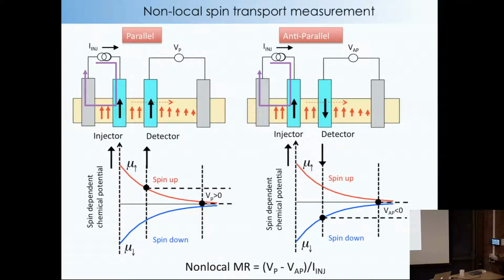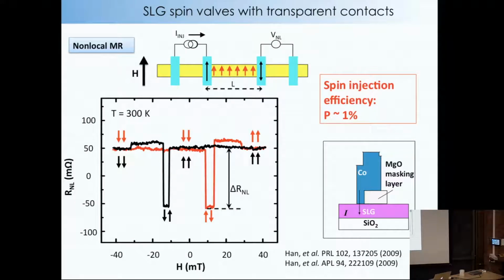So what you typically do is compare the parallel configuration with the anti-parallel configuration. And typically you normalize by the injection current. I mean, if you pump more current in, you'll get more spin density and your signal will be bigger. Okay, so typically you'll normalize this, and this is typically called the non-local magneto resistance, because it's voltage divided by current. And this is a typical data set, and this is for real.